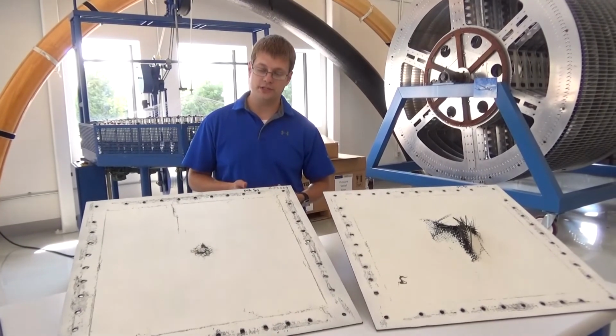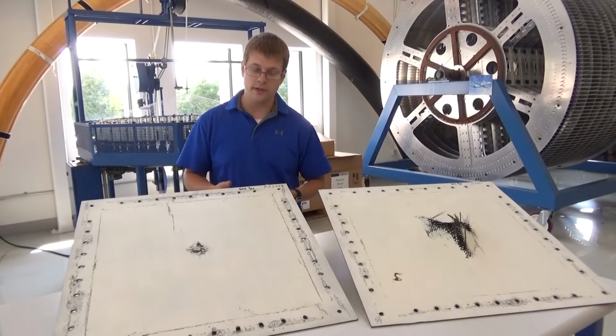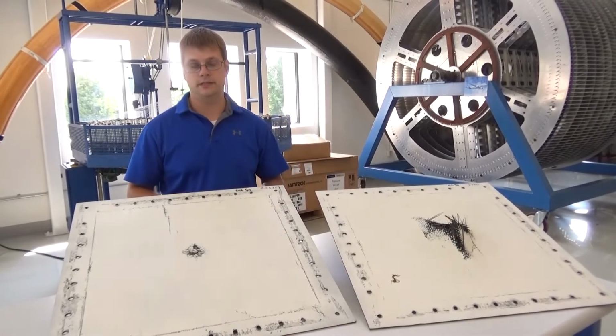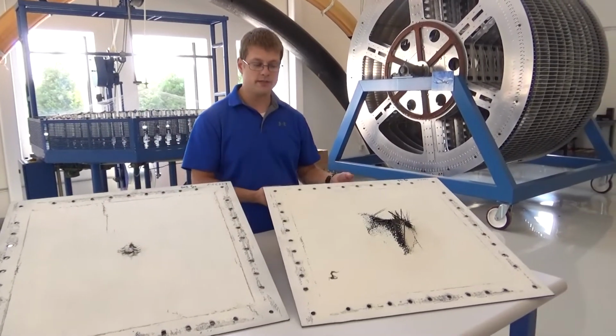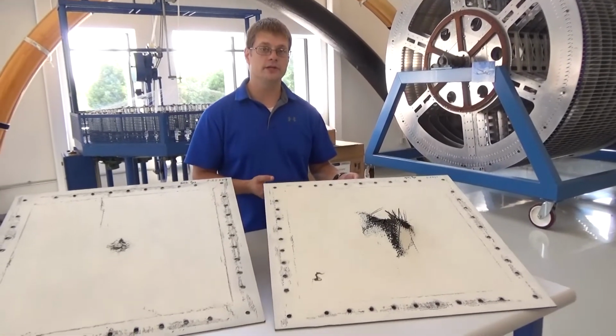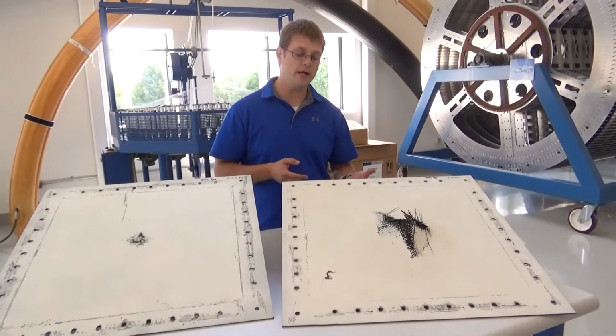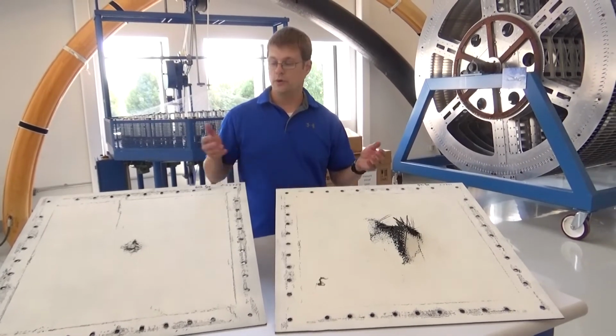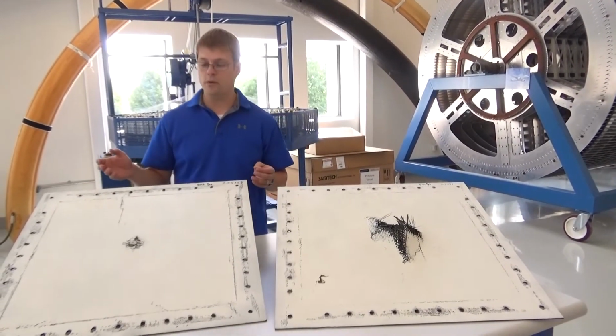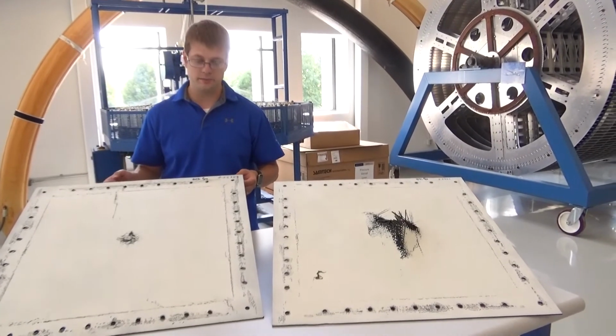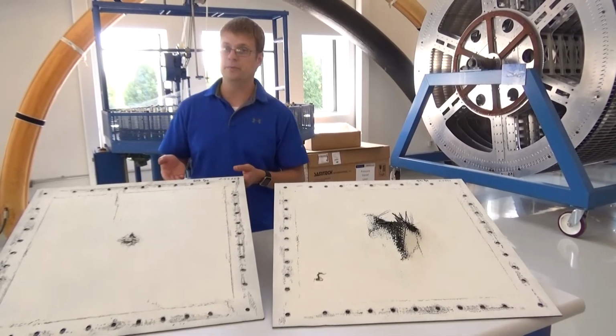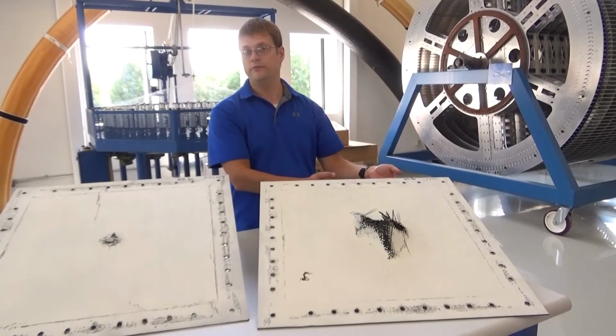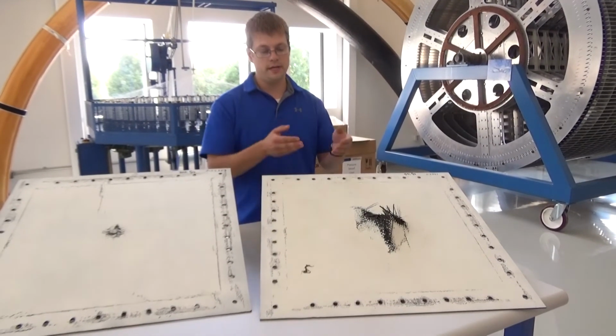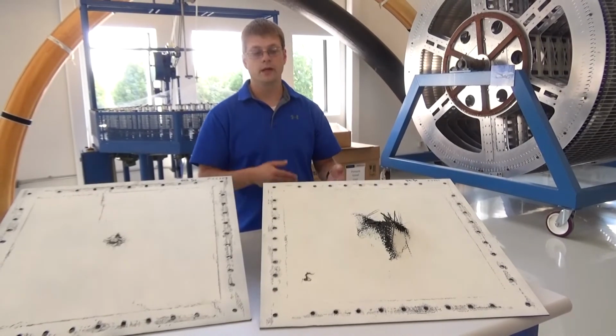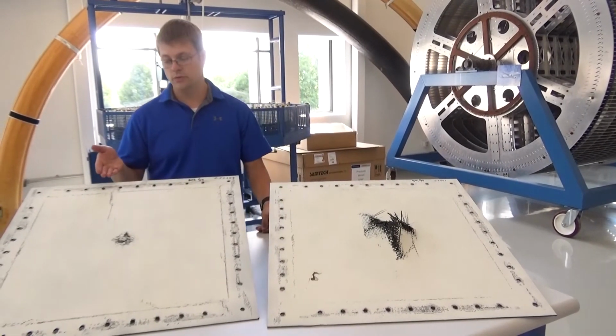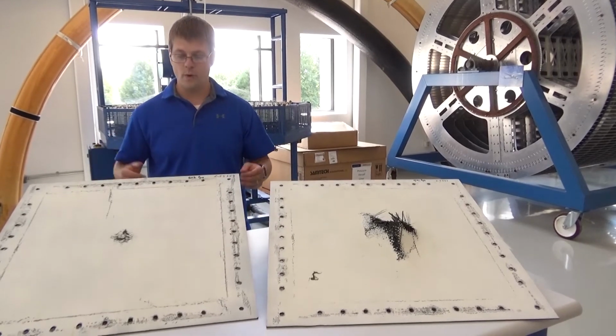So that helps to decrease your interlaminar shear, and it helps all of the layers act more as a net system. With the plain weave, even though you're quasi-isotropic in the laminate, each layer is going to see loads differently. And because of that, you can get internal shearing. So the final results you can see here, we shot a 1 pound gelatin projectile at these panels. This is at 602 feet per second, and this one's at 591 feet per second. As you can see, the plain weave material was uncontained, while quasi-iso remained contained for the same weight gelatin projectile.